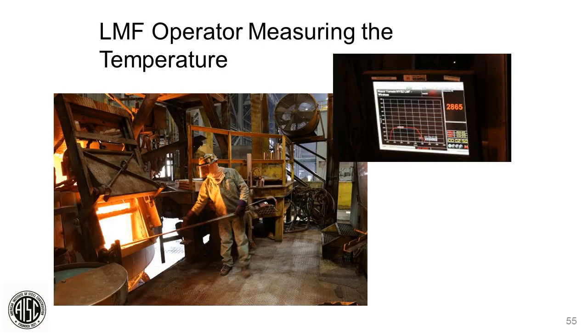This shows some of the technology here. We've got an operator getting a sample. It's a wireless thermocouple. Basically, there's a disposable cardboard thermocouple on the tip. He sticks it in the steel. In the top right-hand corner, you can see a temperature of 2865, which is wirelessly transmitted to the pulpit. And so we check the temperature. Next slide, please.